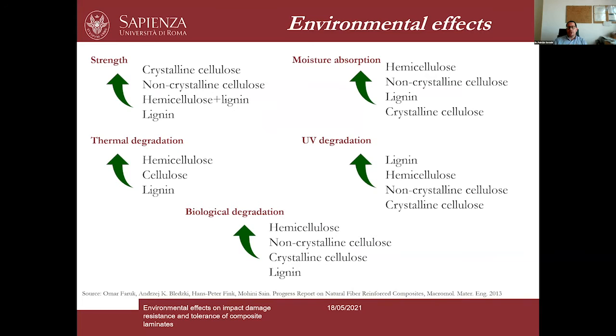And in addition to this hierarchical structure, natural fibers also show properties which are highly dependent on the chemical constituents, and in particular on the relative proportion of the chemical constituents. And basically, natural fibers are composed of hemicellulose, lignin, and cellulose. These are the three main chemical constituents of a natural fiber. And then here in this picture, you can see how these different chemical constituents can affect not only the mechanical properties, in this specific case, the strength, but also, I would say, the degradation properties of these fibers. So in terms of moisture absorption, UV degradation, thermal degradation, and biological degradation. So this is another issue that we need to consider.